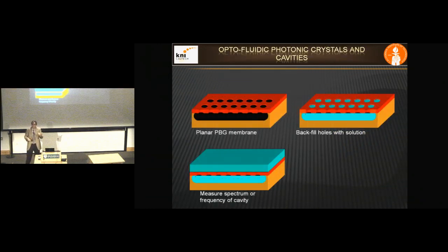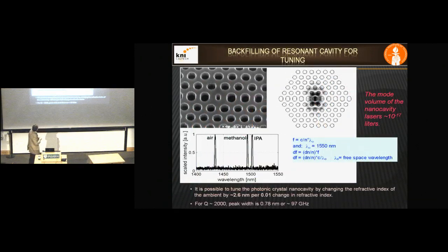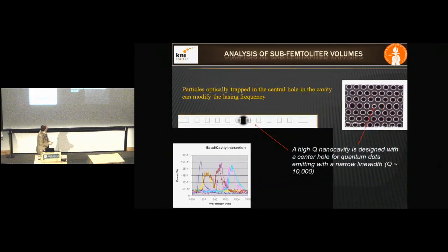Then I can take these lasers that are these structures with little holes in them, and I dip it into a solution, and when the thing lases, it tells me what's inside of the little hole in the middle. And in fact, I can see the difference between methanol and isopropyl alcohol or water by simply looking at the laser wavelength, the laser coming out. All right? And I'm measuring something on the order of 10 to the minus 18 to 10 to the minus 17 liters, because that's the mode volume of my laser. Okay? In fact, this is what the mode looks like. It's concentrated right in this hole in the middle.